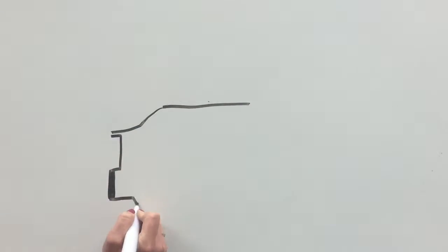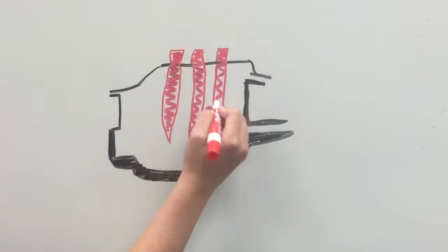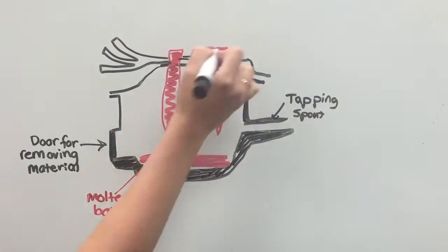One technique for forming boron carbide is the solid-state diffusion between boric oxide and carbon in an electric arc furnace. The reaction produces a boron carbide powder, which is then sintered down and condensed to produce the desired product.